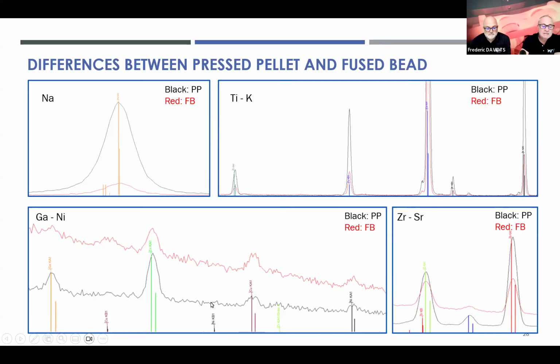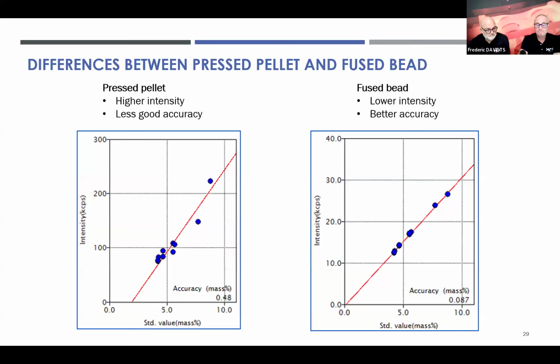So we can also already see the movement of the background is much flatter for pressed pellets than it is for fused beads. So these are all indications that detection limits are way better for pressed pellets. At a certain stage, we can see, for example, here gallium. Here for the fused bead, we are not sure anymore. Is this still a gallium peak, or is this just movement of the background? But for the pressed pellet, we can clearly see, no, this is gallium. We can still analyze it by pressed pellet and not anymore with a fused bead.